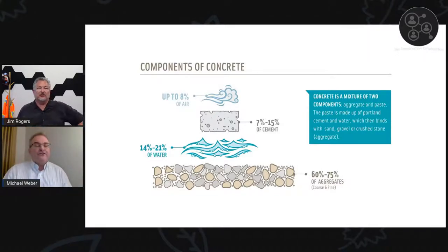Every manufacturer is going to do it just a little differently. But the one thing is when we're talking about this 7 to 15% that you show here, it's best to refer to it as cementitious material because most of your mixes today are not just a straight Portland cement or Portland limestone cement mix. They will typically have fly ash in them where fly ash is available, maybe up to 15 to 25%. Or in some areas, slag cement is more predominant. And slag cement, they will run that from anywhere from 30 to 50%.